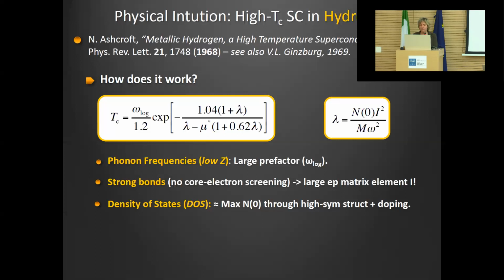So why should this matrix element be large in hydrogen? The reason is that there are no core electrons in hydrogen. So this means that the interaction between the nuclei and the electrons is unscreened. So this bare interaction is strong. And as soon as you displace the nuclei from their equilibrium position, the electrons feel this displacement and react. And this means that they will have a strong electron-phonon coupling.